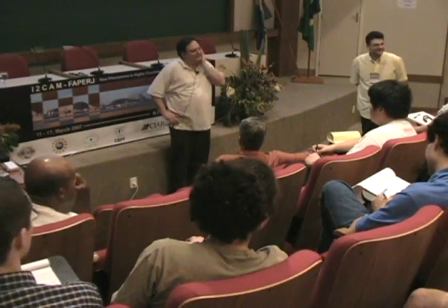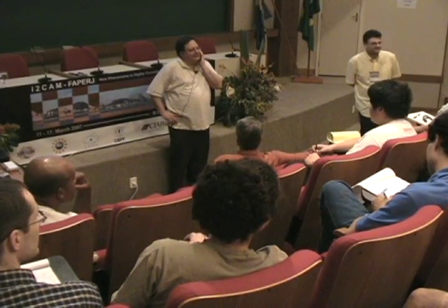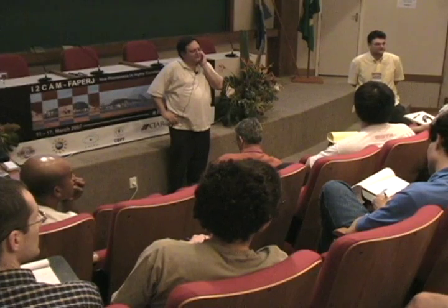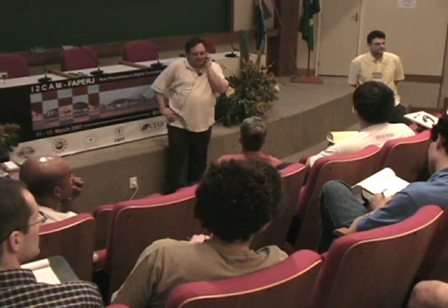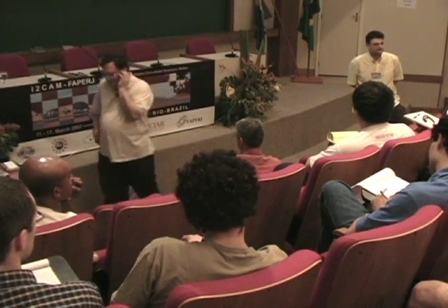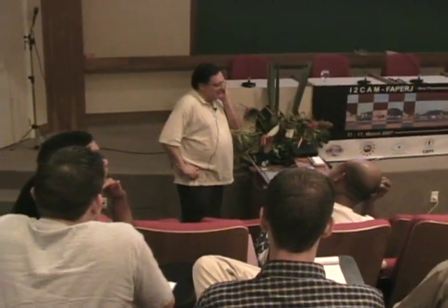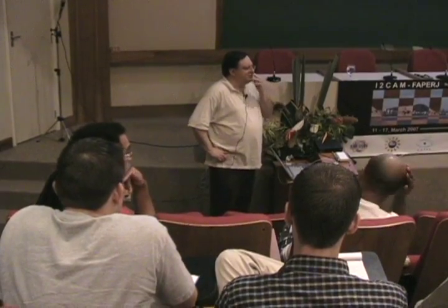It's a relevant question. If the renormalization of the Fermi surface is driven by lattice excitations, it's a very different picture from one in which it's driven by magnetic excitations. Correct, I do care. But there's no way to tell, other than what Chen or Lanzara, somebody, did: an experiment where they changed the isotope. They see that the kink energy shifts by a few millivolts, 3 millivolts or so. So that indicates there is some influence from the phonon.